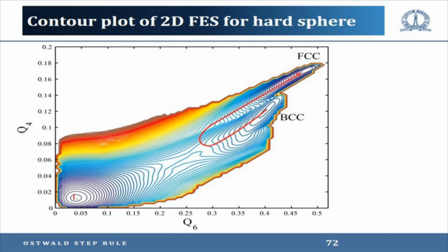We did some simulation and we found a very interesting thing. From liquid, we studied the very difficult calculations of finding the free energy. This is a contour. When it circles like that, that is a minimum. Then when it becomes like that, that is a maximum. This is the saddle. We start from here, we always go to BCC. We never went to FCC. I envisaged it must be something like that, then it goes like that. But we never find that.